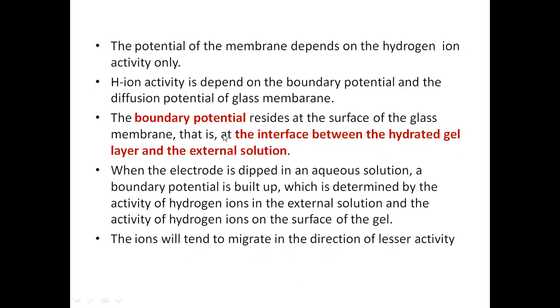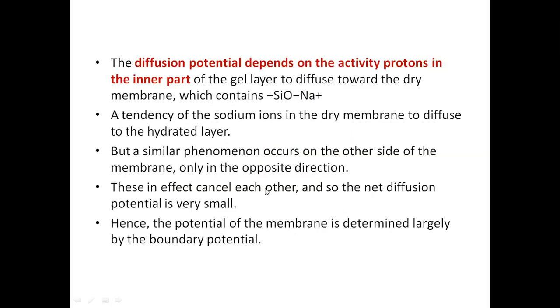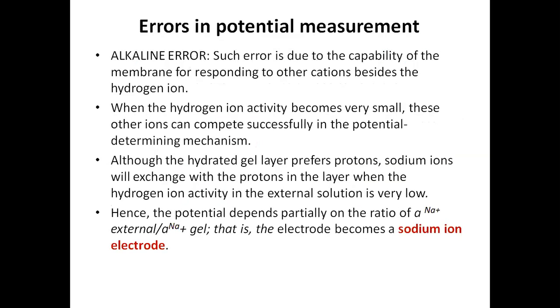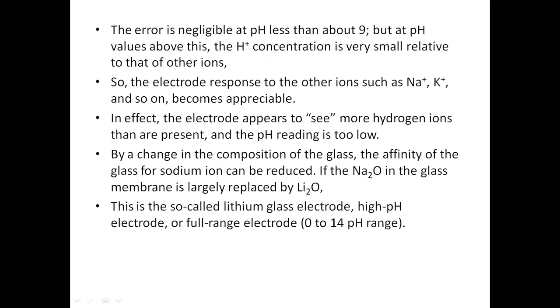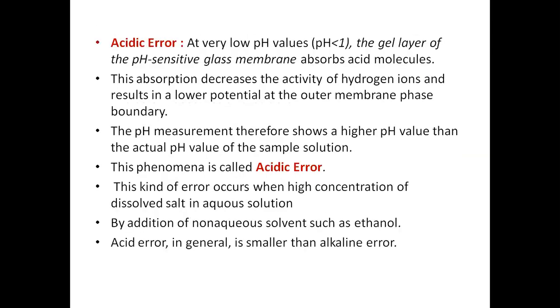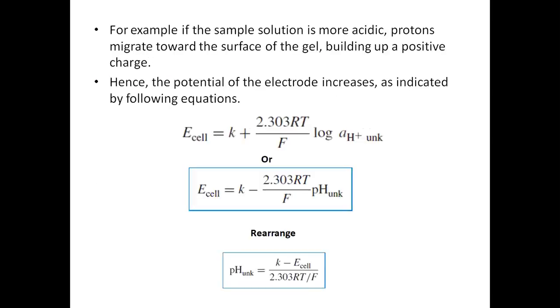Now, what is the boundary potential? It occurs on the outer side of the glass membrane. Diffusion potential takes place on the internal side of the glass membrane, and there are some errors while we take the potential measurement. Alkaline error takes place when we use a highly alkaline solution, more than 9 pH, and the acidic error takes place when we take a highly acidic solution for the measurement where the pH is less than 1. So this is all for today's lecture.